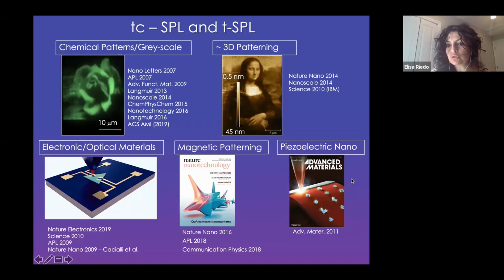And finally, you can use it for local crystallization. You can use a sol-gel of a ceramic material, and the heat can be used for the local crystallization, for example, of ceramic nanowires like PZT, so ferroelectric and piezoelectric ceramic nanowires. Or, going back to electronic materials, you can use it for reduction. For example, you have graphene oxide, and by using heat, you can reduce graphene oxide back to graphene. So again, it is a thermochemical reaction locally activated by the hot probe.